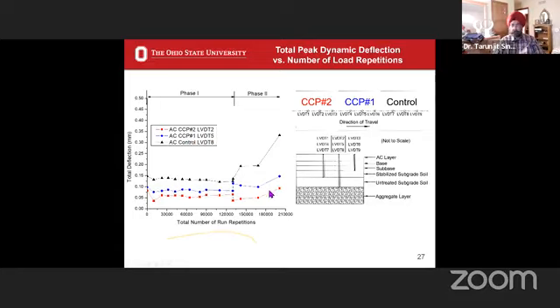So this shows you that the CCP sections perform slightly better than the control section during phase one, just structural loading. But as soon as we introduce environmental effects, the CCP sections saw a little bit of degradation, but the control sections completely went out. In fact, we saw significant rutting.